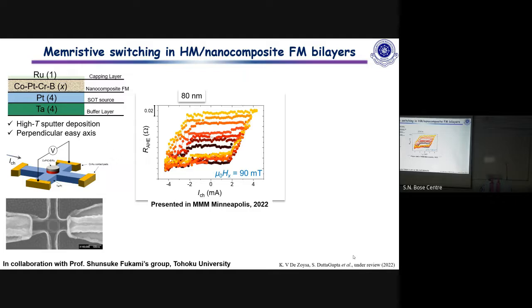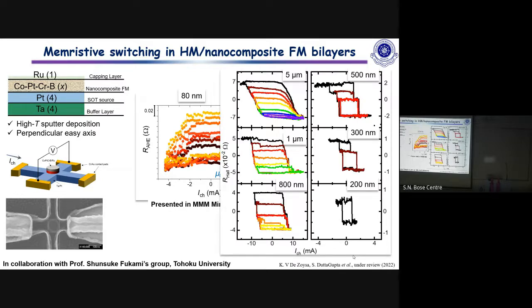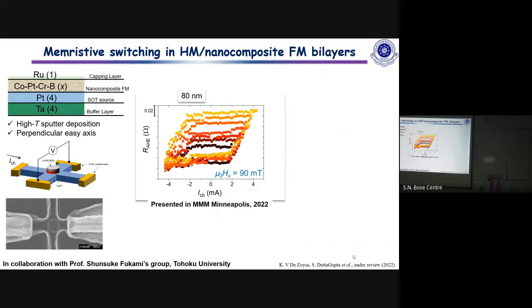Why does it go away at lower dimensions? In our previous work, the switching happened across several different ferromagnetic domains, and the domain size, in our understanding, was probably dictated by the antiferromagnetic domain size below it. The antiferromagnetic domain size was roughly 200 nanometers, so once we go below that dimension, it just shows binary switching. But here the domain size is governed by the energy scales inside this material, and it is around 20 or 30 nanometers. So we can have multi-level behavior even at much smaller dimensions, and we are not restricted by the earlier problems.